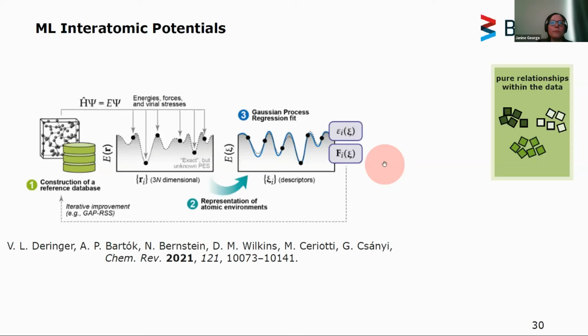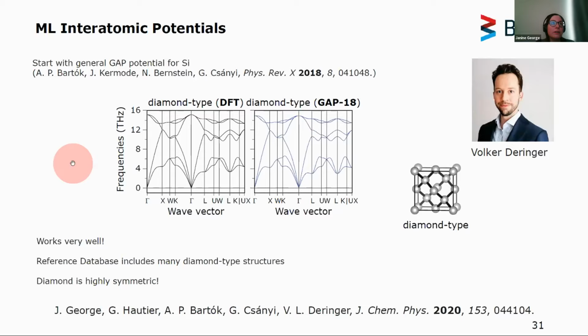We then started with a GAP model for silicon that was developed in 2018 with a lot of data on diamond type silicon, on defect structures, grain boundaries, and so on. And we computed phonons, the phonon band structures, the vibrational properties for this diamond type silicon. And what we saw is that the result from the GAP18 model was agreeing very well to the DFT data, that this worked really well. But as I said, it's not really a surprise as there are many diamond type structures in this kind of database.